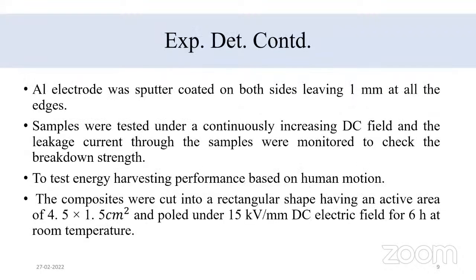Now for the formation of the device, that composite film was aluminum coated on both sides, leaving 1 mm at the edges. The sample was tested under a continuously increasing direct current field, and the leakage current through the sample was monitored to check breakdown strength.